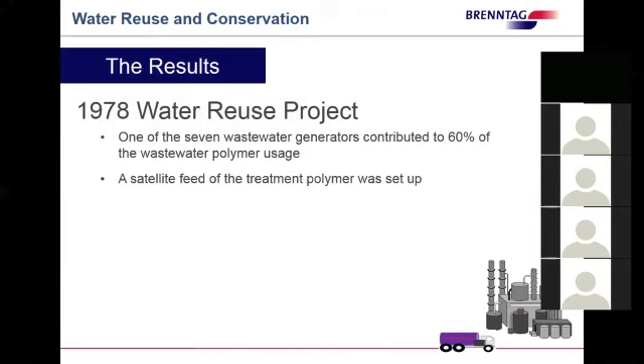What was nice about this is then what we did is we actually went into the plant and we were able to set up a satellite feed of a different polymer, interestingly, to that particular system, that particular generator. And luckily, they had an API separator. And if anybody doesn't know what an API separator stands for, American Petroleum Institute. And it's nothing more than a wide spot in the line that allows oils or solids to settle out to take loading off the system downstream. So here we were actually lucky that there was an API separator there. So we were actually able to pre-treat this material and remove the contaminants before it got to the main waste treatment plant.